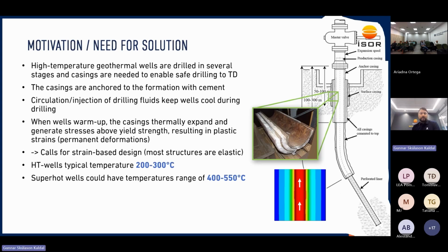The casings are anchored with cement all the way to the surface. And during drilling, there's a circulation or injection of drilling fluids that keeps the well cool. When the drilling has been completed and the well starts to heat up, the casings will thermally expand, and normally they will develop stresses that are above the yield strength of the casing material. And that produces permanent deformations or plastic strains in the steel.